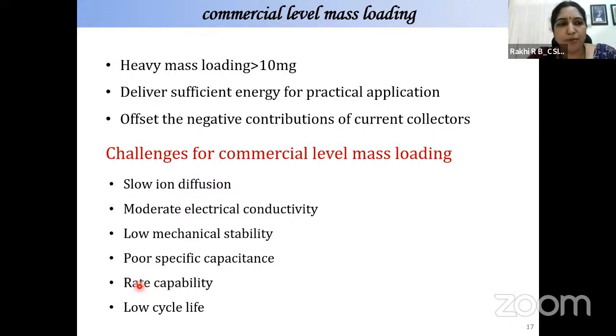Okay, a mass loading per active material per electrode of about 10 milligram delivers sufficient energy for practical application. Even if you fabricate in the conventional way, if you retain your active material mass at about 10 milligram, you can avoid the negative contribution from the current collector as well as the binder in the overall device capacity.